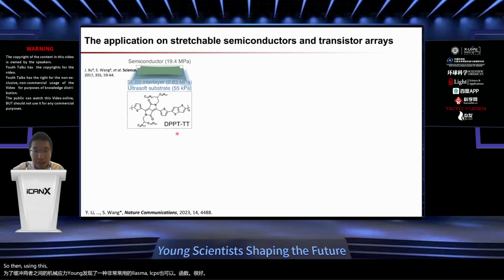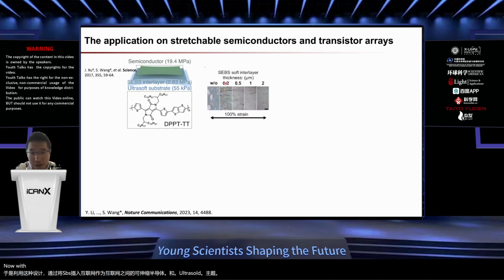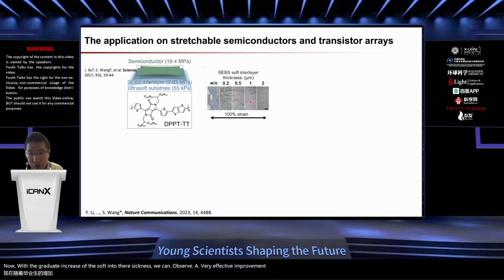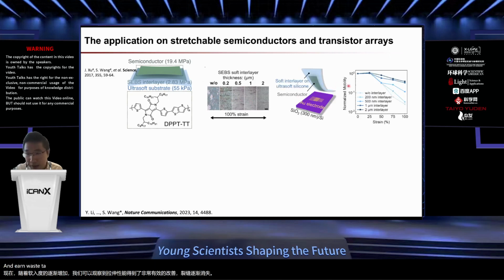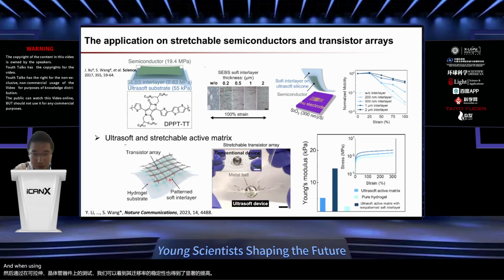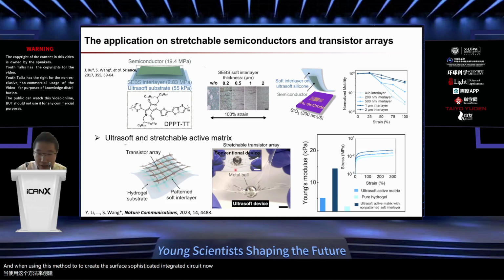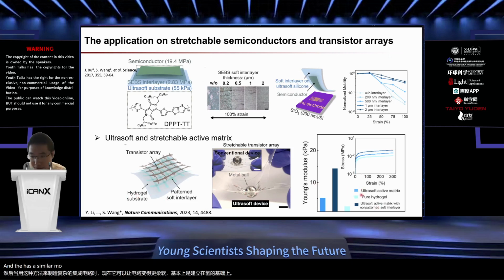So using this design, by inserting the SEBS as an interlayer between the stretchable semiconductor and ultra-soft substrates, with the gradual increase of the soft interlayer thickness, we can observe a very effective improvement of the stretchability. The cracks gradually go away, and when it's tested in the transistor device, we can see the stability of the mobility also gets significantly improved. And when using this method to create a sophisticated integrated circuit, it allows the circuit to be much softer. Basically, it's built on hydrogel and has a similar modulus to hydrogel, but can perform in a highly stretchable fashion.